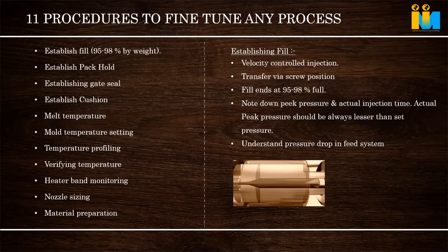What happens in the stopping? The raw material cools down. Plastic is a non-Newtonian material. When the flow stops, pressure reduces, and when flow stops, its temperature will drop, and vice versa. So we should not do a premature switchover. We have to fill the part to almost 95-98% by weight, and not by shape. By weight means we can measure the weight of the part on a weight balance. Then switch over to holding and give the packing desired to compensate the shrinkage and sink mark, whatever it may be. This is the first phase.